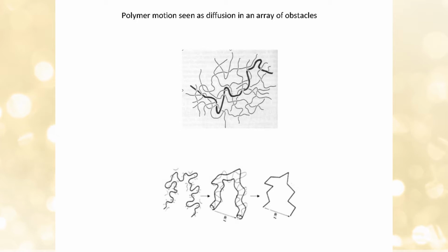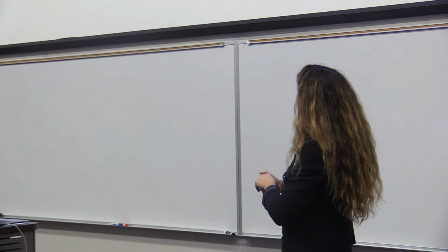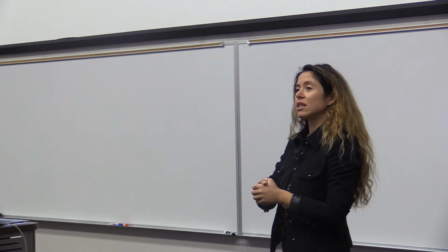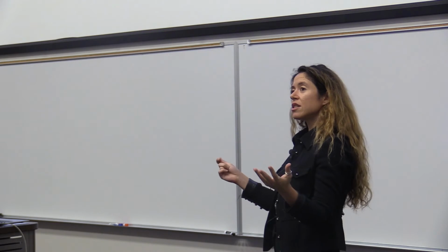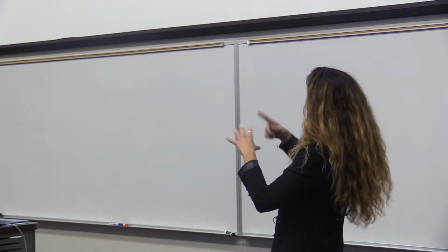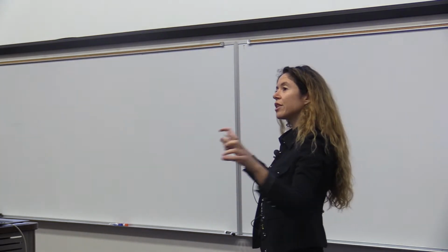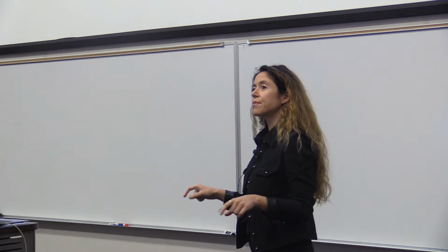When we study polymer properties, one can see the effect of entanglement arising. You have many chains, all of them entangled to each other like spaghetti, and you want to understand how they move and how that affects their mechanical properties. The idea is that if you imagine one chain, the one highlighted there, tries to move, and suppose the other ones are fixed around it, then it cannot move anywhere it wants, but has to diffuse within this imaginary tube-like region formed by the surrounding obstacles.